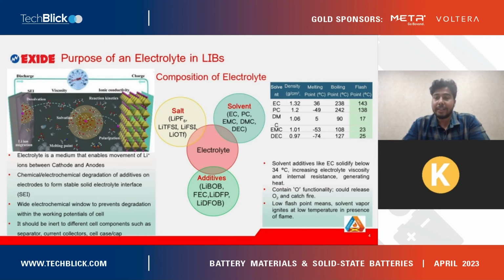Which is compromising the safety of batteries, and even the other part like EC tends to solidify at room temperature, so increasing viscosity that we see in LFP batteries, basically. At low temperature its performance is low because slow ionic diffusion is the reason, and again another reason is the viscosity increase in the electrolyte. So the problem is with the safety issues and the heat generation. If there is any heat generation, then there is a chance of thermal runaway. Shrinkage of your separator at 120, even if you have alumina coated. At around 130 degrees it starts shrinking, and then you have micro short circuits, and all these electrolytes are flammable. And apart from that, material degradation is another part.